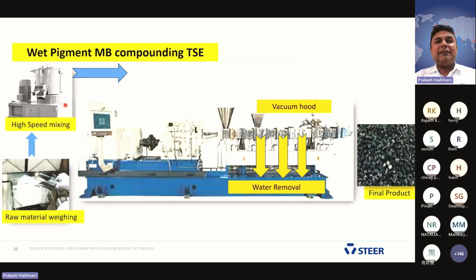This is schematic, not actual. What we are doing is weighing all the ingredients and putting them in a high speed mixer. From there, we transfer the material to our feeding mechanism, which feeds and pushes it into the twin screw extruder. The water removal will be done by dry vacuums, removing water in 3 locations, and then stranding and pelletizing will be done.